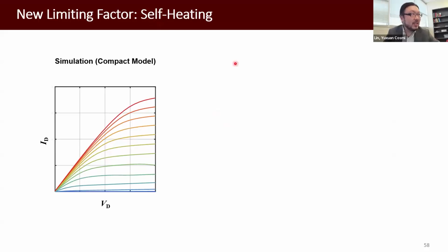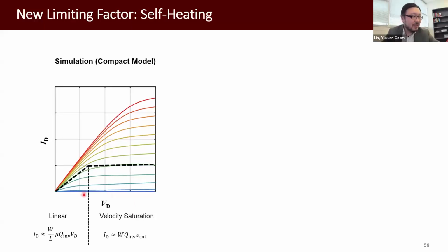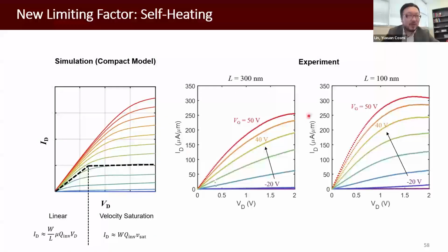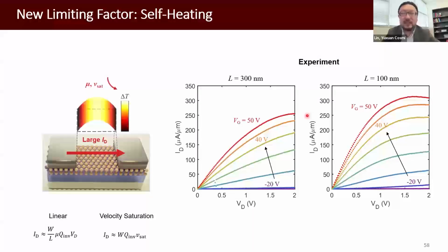So it's basically self-heating. This is the ideal IV curve for a transistor from a compact model. We have a linear regime and a velocity saturation regime for the ID-VD curve. But if we look at our experiment, there is a saturation, but the shape is different. Especially for this case, there's a negative differential resistance. Those are the typical features of the self-heating effect.